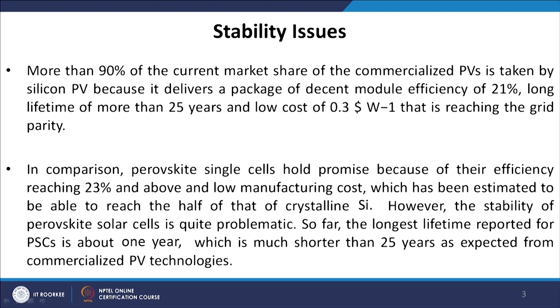Silicon PV delivers a package of decent module efficiency of 21 percent, long lifetime of more than 25 years, and low cost of 0.3 dollars per watt, reaching grid parity. Once you install it on your rooftop, you do not have to be concerned for the next 25 years. Because of continuous research, this is a very mature technology. The cost is around 0.3 dollars per watt.